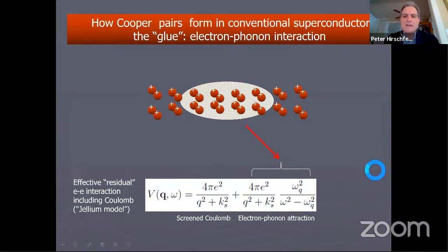When you do a simple calculation that is associated with this picture, you find that two effects have to be taken into account. First of all, there's always the screened Coulomb interaction between electrons, which is always repulsive. And then there's the electron-phonon interaction, which can be attractive in a certain frequency range. You notice that if omega goes to zero, these two terms in this particular Jellium approximation actually exactly cancel each other. So you might think that superconductivity would always be absent or very weak.